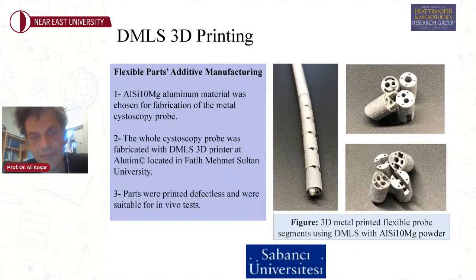probe. And for the final ones, we used aluminum alloy, and we use this version in vivo tests, and it's more durable. At the same time, it's also rather light. So we used a metal printer located at Fatih Sultan Mehmet University, and we could fabricate the needed parts, which were defectless and which were also suitable for in vivo tests. And you can here see the fabricated metallic versions of our probe.